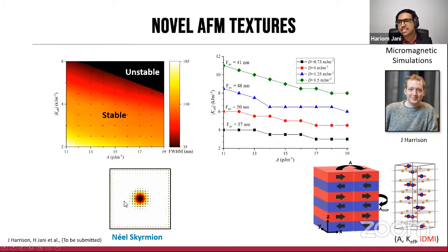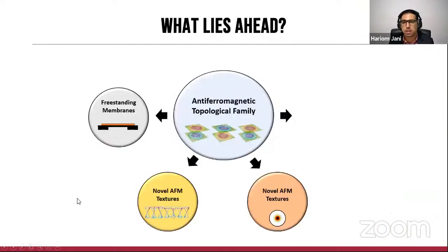To just give you a slight estimate, for this range of stability for a set of standard values of exchange that we use in the system, let's say in the window of about 14 picojoule per meter, we actually have a wide temperature window where the anisotropy is tuned below the Morin transition. And this, depending on the A value, can be tuned in a wide range of parameters, almost up to 20 to 40 Kelvin, which is a sizable window to actually stabilize these objects. And therefore, there are some interesting results awaiting in the future.